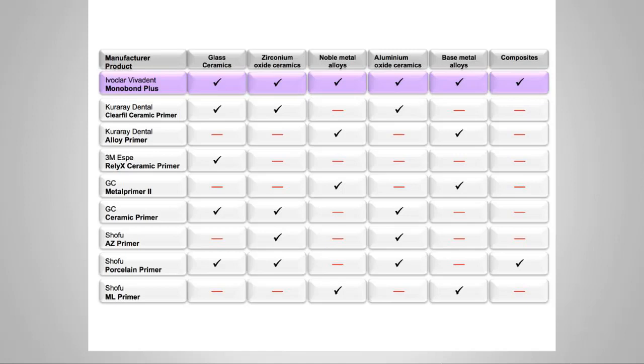This is a chart with a lot of different primers. The one in pink is the one that I use when I do use them. This is what I would use on my lithium disilicate, on my zirconia if I were going to use a primer on zirconia. And you can see the Monobond Plus basically will prime any substrate. Other products don't always prime all of the substrates that you're wanting to use. So I like to keep it simple, and Monobond Plus allows me to do that.